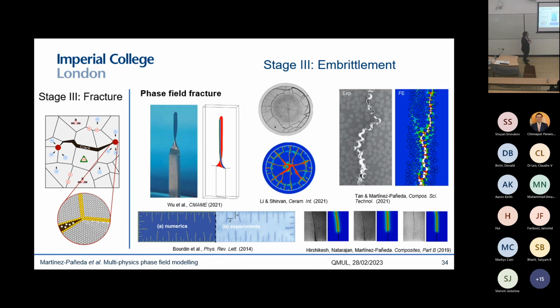And yeah, this slide, I hope, convinces you of the capabilities of these kinds of methods, because they're not only useful in being able to capture very complex cracking phenomena, but they're also useful in providing a good agreement with experiments, because they're based on the thermodynamics of fracture. So this, as you can see, provides very good agreement with experiments. And I have incorporated a few examples here from several groups, including some of the nice work that Wei Tan has done with phase field methods in trying to bring insight into the micromechanical behavior of composite materials, which I think also shows quite nicely the capabilities of these methods.